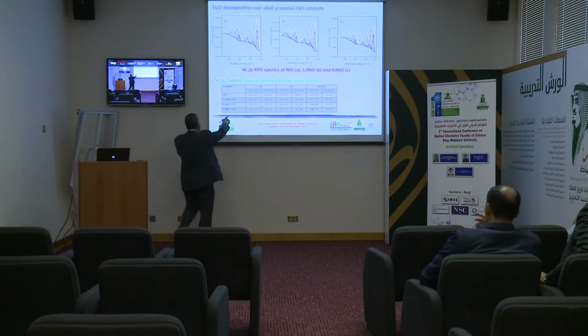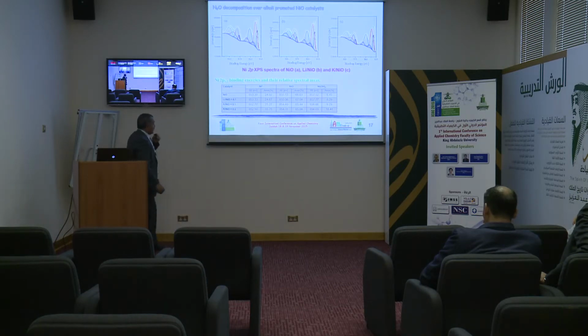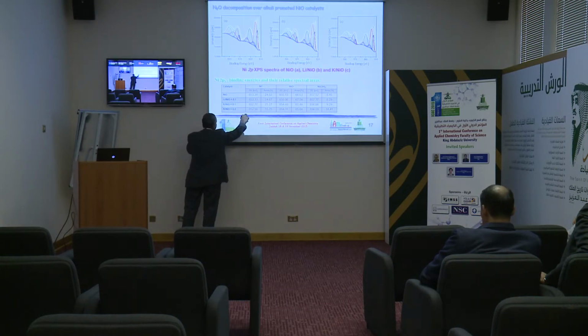The interesting thing is that the binding energy of nickel 0 decreases clearly upon adding potassium, and slightly upon adding lithium as dopant. On increasing the potassium ratio to 0.2, which I'm going to talk about in a few minutes, we can also observe a further decrease in the binding energy.